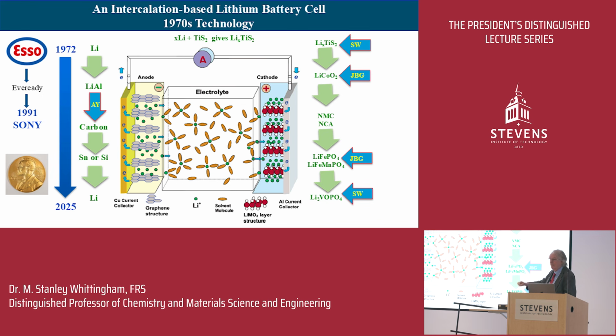This is what we call intercalation reactions. In other words, the lithium goes into these materials between those sheets without changing the crystal structure at all. So if you put it in and take it back out, the structure should look exactly the same. And if you've got a very old dictionary at home, look up the word intercalation. It'll refer to February the 29th. You intercalate it into the calendar every fourth year, then you take it back out and the calendar is back to where it was. So this is what we've been working on, a lot of work on every component of it. So we started out in '72.